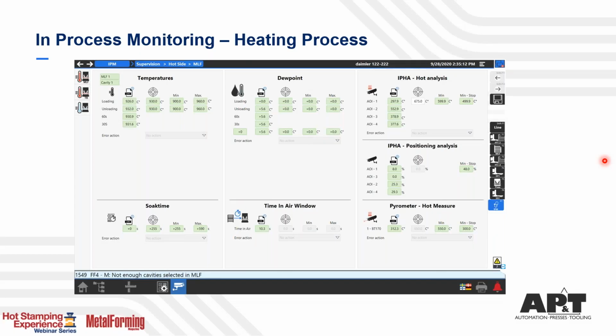This is a screenshot of our main panel on the HMI, the human machine interface. It shows the monitoring and control of the heating process itself. So what do we see? We can monitor temperatures in the furnace. We can look at dew points. This is what we call the inline process monitoring hot analysis when coming in with a hot blank. The positioning analysis, what I said with the positioning cameras, and then we have the pyrometer for measuring blank temperature on the hot side. We can also monitor time in air window and, coming back to the furnace, soaking time.